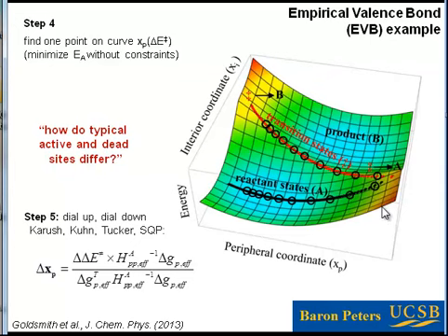So the path that we're following is guided only by the criteria that I want the activation energy to get bigger and I want the activation energy to get smaller. In fact, it is answering the ill-posed question that I posed to you in the beginning, where people say, let me just try and move the atoms around so that I get a higher activation energy. Well, this is telling you exactly how you should move the atoms so that you get a higher activation energy without paying a lot of site formation energy price for doing so.